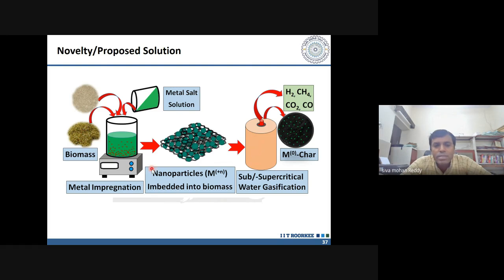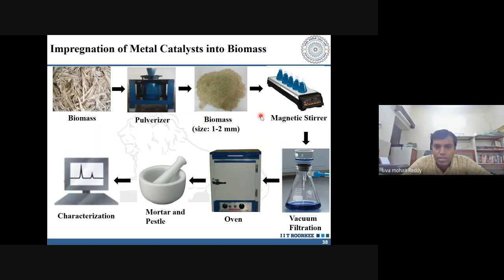Then we mix it with the metal salt solution. If you are using nickel, it is going to be nickel nitrate. If it is ruthenium, it is ruthenium chloride. If it is iron, it is going to be iron chloride. Okay, and when you are mixing it in the metal impregnation process, the metal particles get associated with, or get absorbed onto, your carbon matrix. This nanoparticle embedded biomass matrix now has the metals inside it. These metals act as a catalyst during the degradation process and thereby promote hydrogen production.